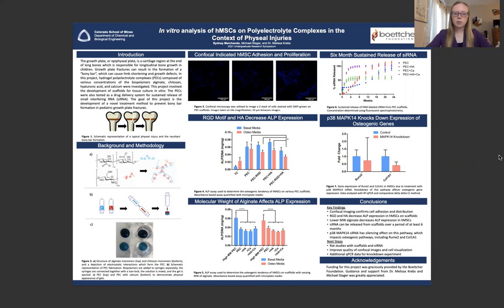Utilizing confocal microscopy, the distribution, adhesion, and proliferation of the cells was able to be visualized. The cells were stained with DAPI, which targets the nucleus of the cells, and the images shown at the center of the poster were taken at 10x magnification. Each image is taken 10 microns apart from the last, showing the distribution of the cells into the scaffolds. Various combinations of scaffold materials were tested to determine their impact on human mesenchymal stem cell growth and differentiation.